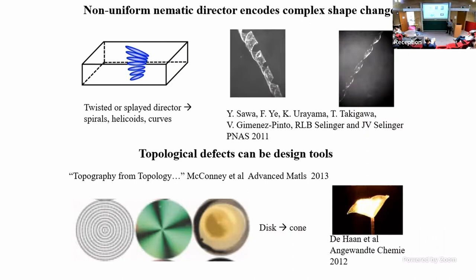And then we can actually inscribe topological defects into these materials. So for instance, if your director is arranged along azimuthal lines, and then you heat the material, a disc will turn into a cone. And this picture is from the Eindhoven group, Dick Broer's group. Lawrence DeHaan was the graduate student at the time. So this started flat here. He sucks the material onto a little glass tube just to hold onto it, and he heats it up and it turns from a disc to a cone. Okay, this is not how you're going to be opening your umbrella, but you know, it could.